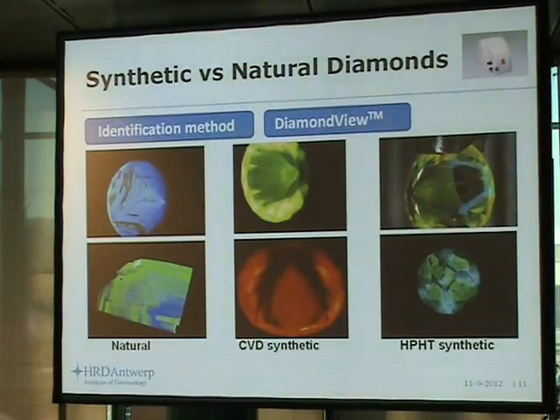And the way that these diamonds grow, one standard way for our lab to look into that is using the Diamond View instrument. It's developed by the Diamond Trading Company, and it uses a shortwave UV illumination to get the surface luminescence. Not only color, but also the structure can be visualized quite nicely. And what is typical for a natural product is that it grows over a long time, gets deformation, and that results in quite irregular structures. Different colors perhaps. If you compare that with synthetic growth, you see it's very symmetric. For example, very typical high pressure, high temperature diamonds are very symmetrical. Cubo-octahedral symmetry is coming back.